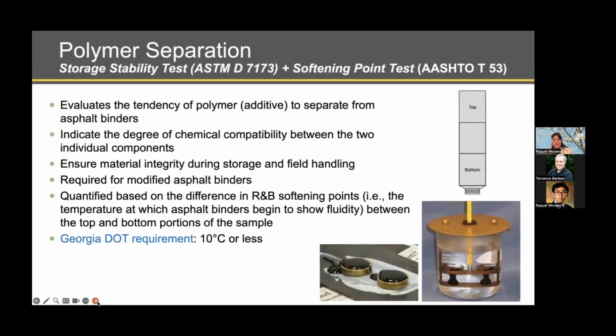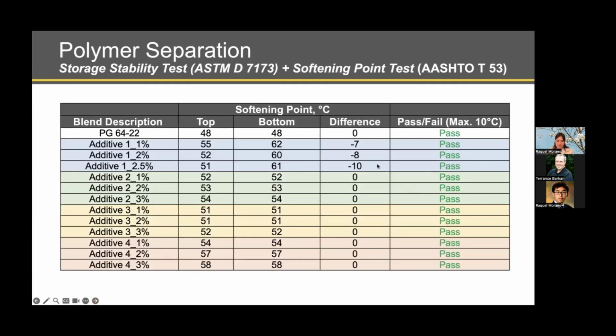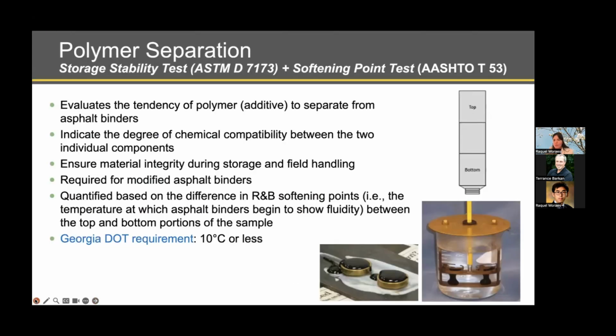The first test that we evaluate was the storage stability test. It's an ASTM standard, and is used for us to evaluate the tendency of a polymer to separate from one additive that is incorporated into the binder. Following the storage stability test, we perform a softening test to see the tendency of the specific additive to be separated from the asphalt binder.